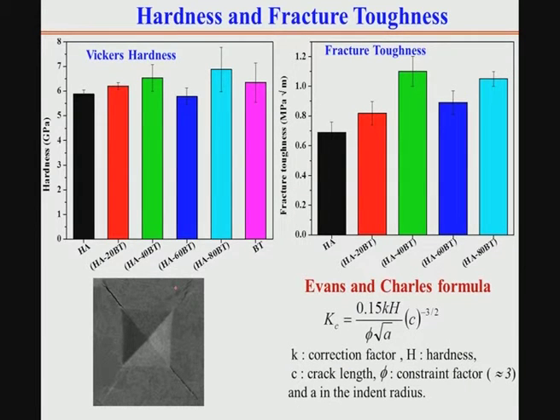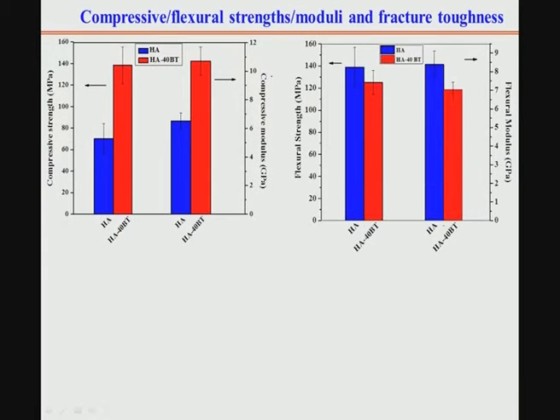Now, other things that we have measured as part of the physical property measurements are Vickers hardness and fracture toughness of these materials, and as you see, they show very normal, moderate values. First of all, fracture toughness was measured here using indentation toughness, not SEVNB, and it does not really show very high indentation toughness, about 1 to 1.1 MPa square root meter, whereas Vickers hardness is around 6.5 gigapascal.